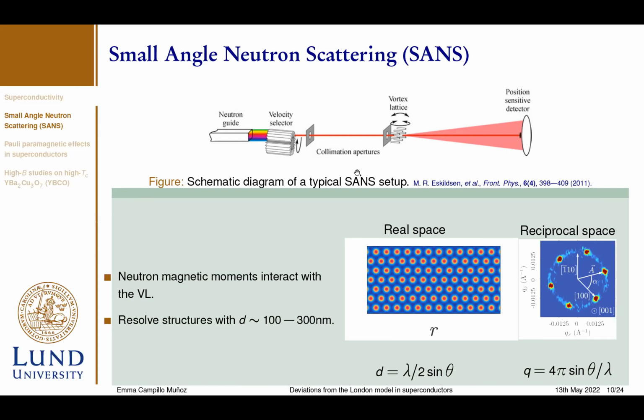Since neutrons carry a magnetic moment, they are able to interact with magnetic structures, and they will be able to interact with our vortex line lattice as well. The diffracted neutrons will be detected by a two-dimensional detector, and the unscattered neutrons will be collected by a beam stop at the center of this detector. As I mentioned before, we use neutrons because they have this magnetic moment, but we also use small angle neutron scattering because we can resolve structures with a big d spacing. From vortex structures that look like this in real space, we expect a reciprocal space picture like the one I show on the right-hand side.